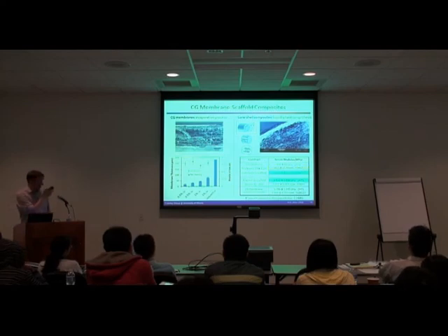So let's look at some properties here. If you look at the membrane itself, it has a modulus of about 45 megapascals, which is much higher than anything we see in a scaffold. For example, a classic scaffold might be in the kilopascals if you're lucky, and that's nowhere near the 150 megapascals you see in tendon itself.